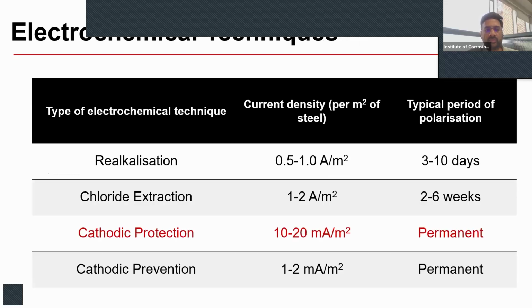Electrochemical systems can cover electrochemical realkalization, chloride extraction, and cathodic protection or prevention. Realkalization and chloride extraction are basically temporary techniques but require a high current density. Cathodic protection and prevention are common techniques but require much lesser current density—for prevention, 1 to 2 milliamperes per meter square, and for protection, about 10 to 20 milliamperes per meter square.